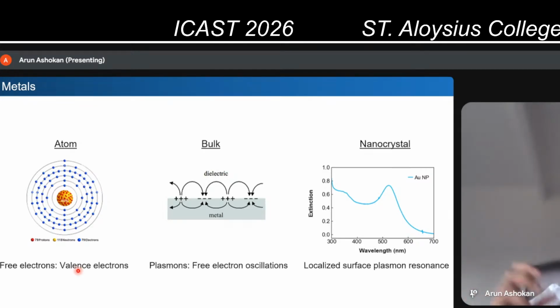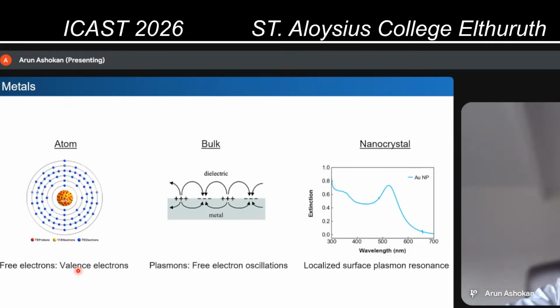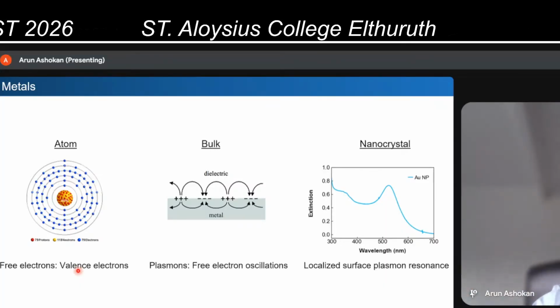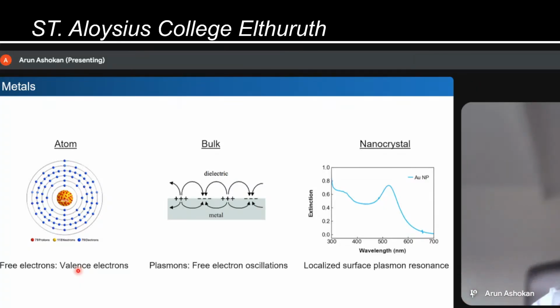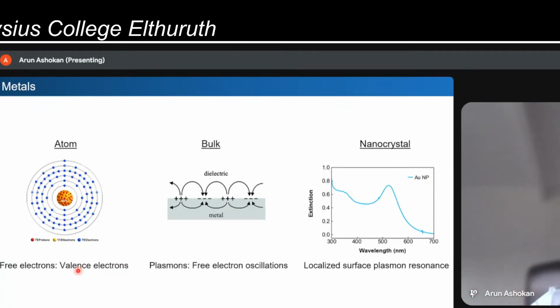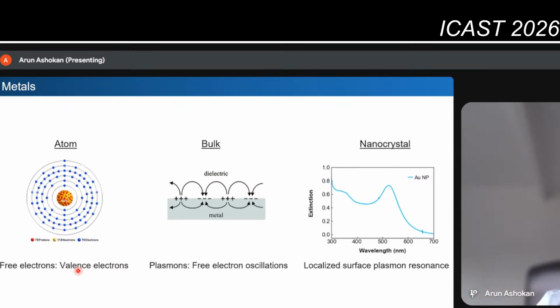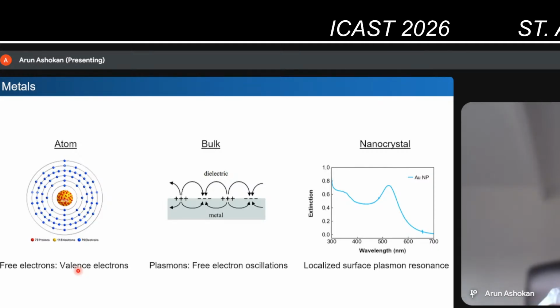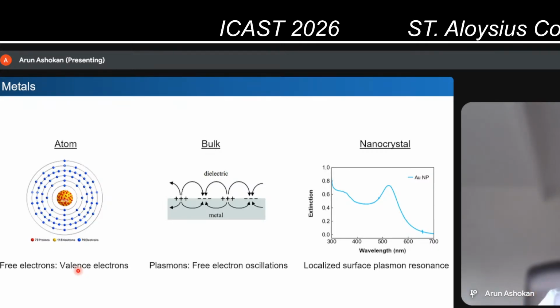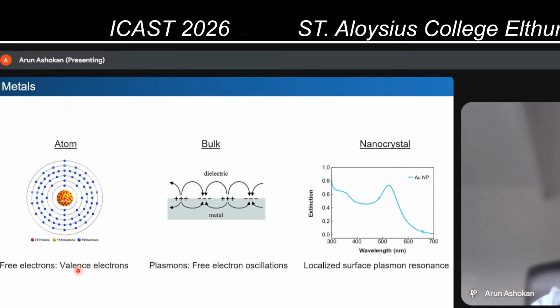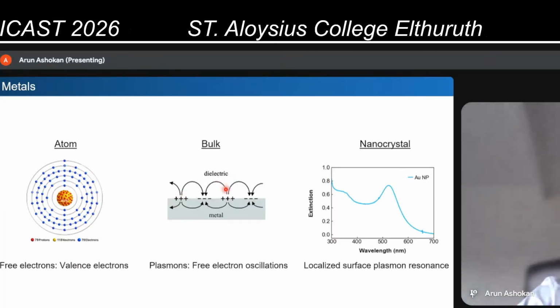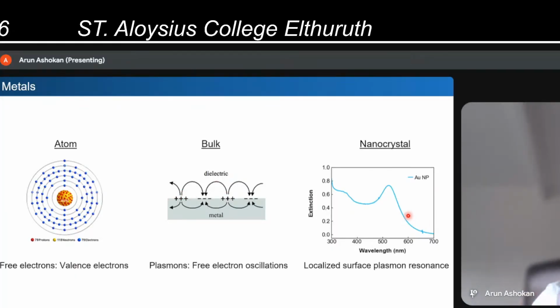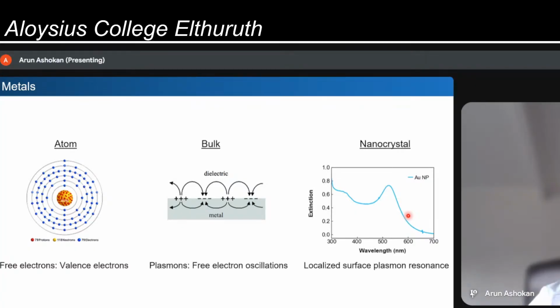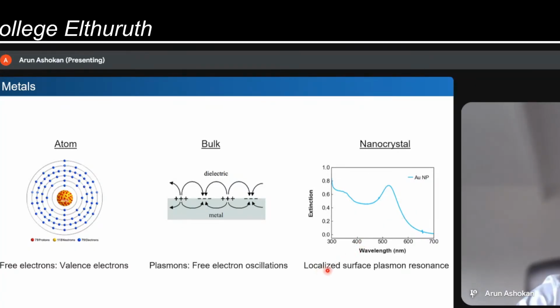When you combine these atoms to form bulk gold, you have a lot of valence electrons, and these free electrons can oscillate, and this oscillation is called plasmons. So there is a quantization of these electron oscillations. That's called plasmon. When you come to nanocrystals of metals, the size of the nanocrystal is confining the plasmon. So the plasmon can't propagate, unlike what it does in a metal. In metal, it can propagate, but in a nanocrystal, it can't propagate because of the nano size of the nanocrystal. So in such a case, these plasmons are called localized surface plasmon resonance.